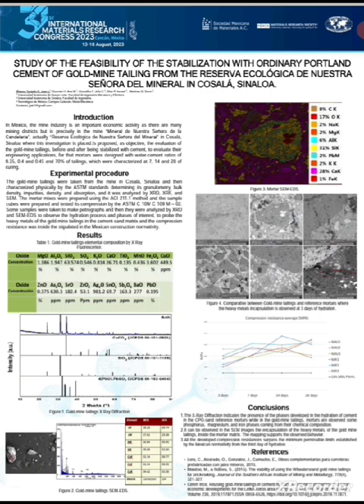The way we did this was taking the gold mine tailings from the mine in Cosalá, Sinaloa, and then characterized physically by the ASTM, determining its granulometry, bulk density, impurities, density, absorption, and fines percent. And chemically, it was analyzed by XRD, XRF, and SEM. The mortar mixes were prepared using the ACI 211.1 method, and the samples were prepared and tested in compression.